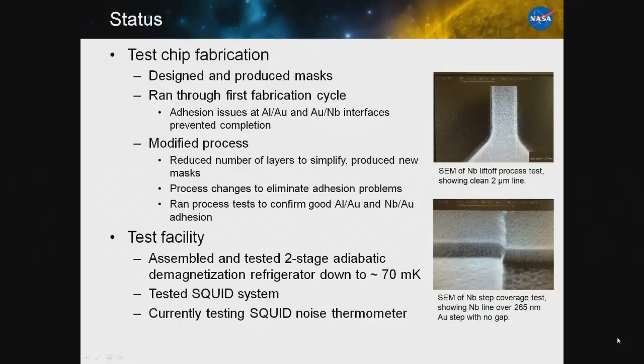But this year we've modified our design to reduce the number of layers. We've produced the masks. At least the masks are supposed to be here. We've also changed our processes. We've figured out what went wrong, eliminated the problems that caused the lack of adhesion, and we've actually gone through and run process tests to confirm not only good adhesion at these interfaces, but low interface conductance.